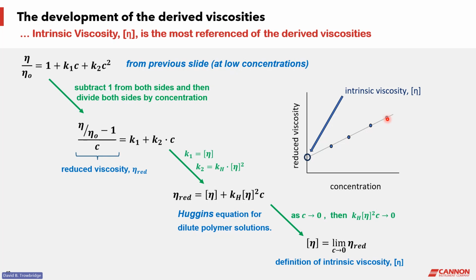We get different reduced viscosities at different concentrations. Then we extrapolate the trend line for these data points to the y-intercept, which is concentration at 0, and the intercept there is going to be the intrinsic viscosity. So this is one of the aspects of analyzing for intrinsic viscosity.